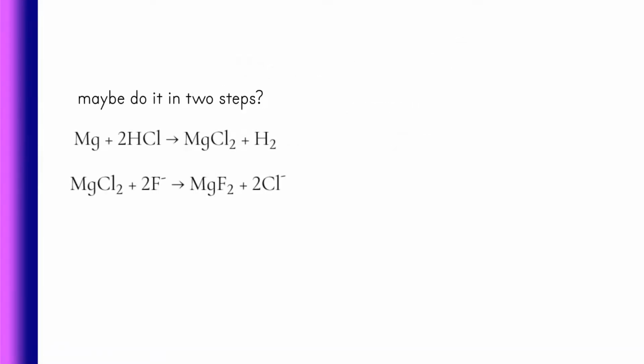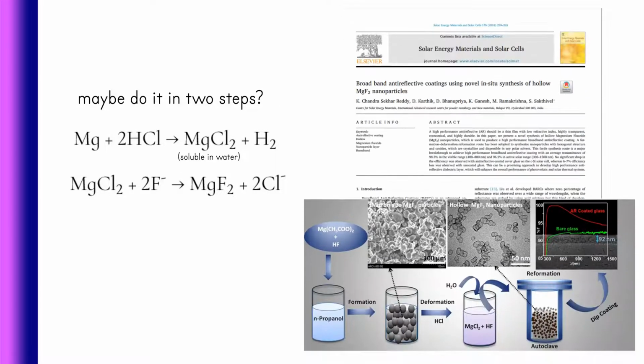I think it's better to, at the minimum, dissolve the magnesium metal into magnesium cation using an anion that's compatible with magnesium, like this paper that uses magnesium acetate and HF in the beginning, which forms the magnesium fluoride, only to redissolve it in hydrofluoric acid and reform it to get nanoparticle-sized magnesium fluoride.